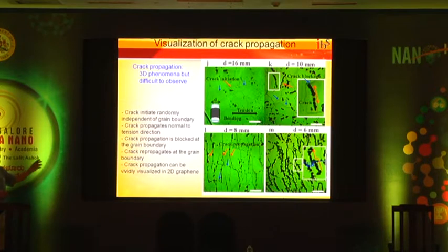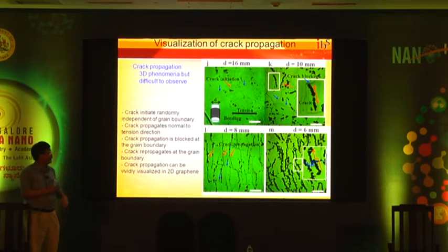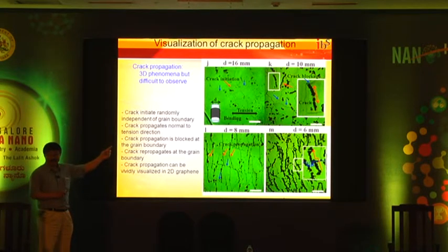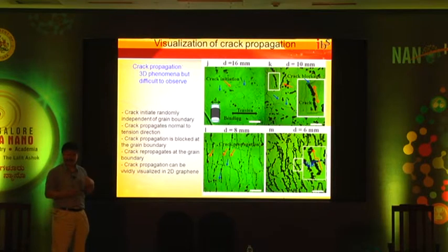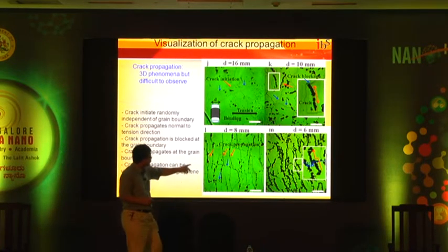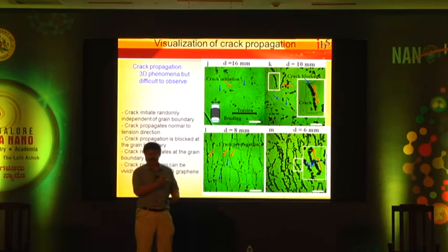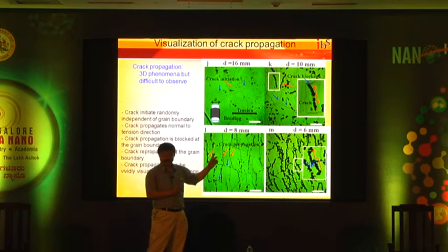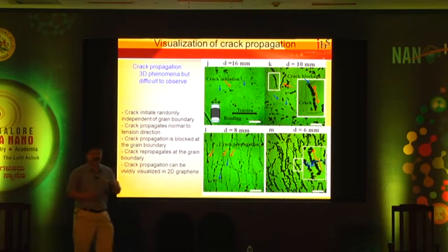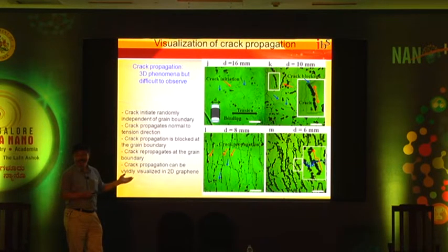Now, once you have this idea, this is one good example you can play with. You can simply wrap this graphene on any kind of pencil, and you create bending. Of course, this bending will generate cracks in the graphene, and if you reduce the diameter of the pencil and the bending increases further, eventually cracks occur. Then you can see the crack propagate, and at some point at the grain boundary, the crack stops, changes direction and then propagates. So crack propagation stops at the grain boundary, which can be visualized very easily using this graphene.